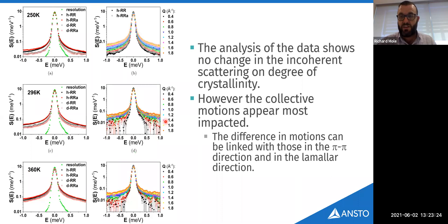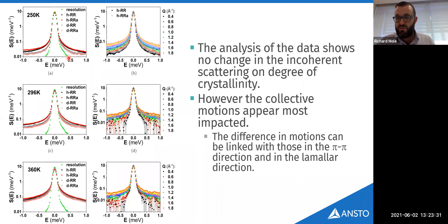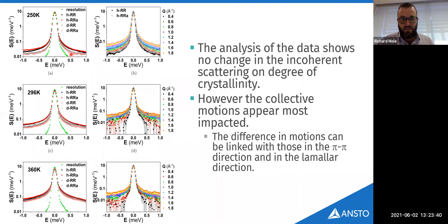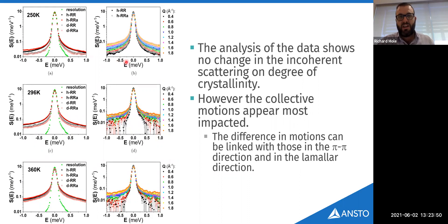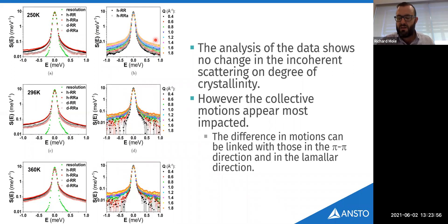The black data is the deuterated polymer and the green and blue are the hydrogenous ones — you can clearly see how much more structural information you get from the pair correlations of deuterated material. The regio-random sample has far fewer crystalline peaks, as expected. Then looking at a QENS spectrum, the green line is the resolution function of the instrument determined using vanadium or a very cold sample, with the different colored points representing the different samples.